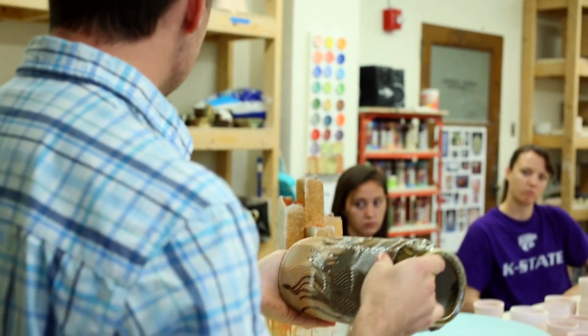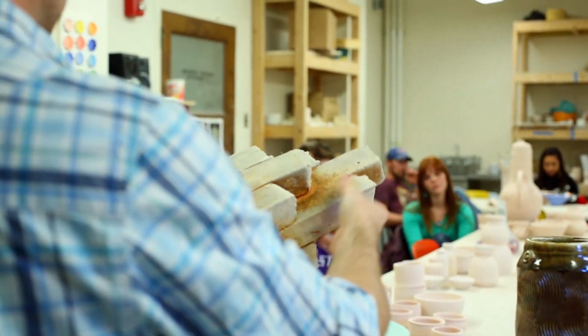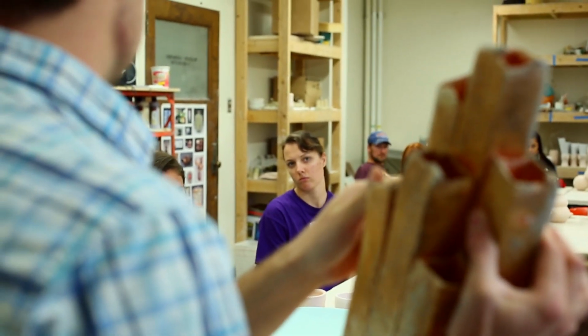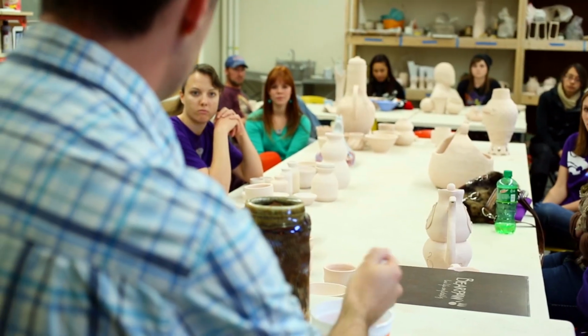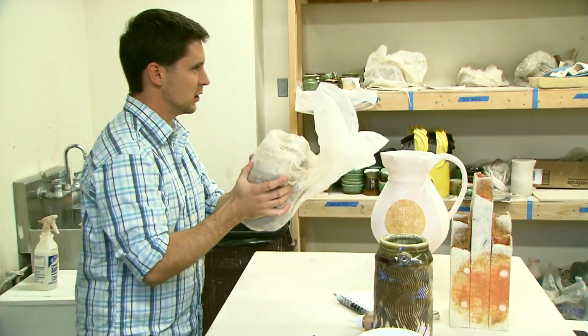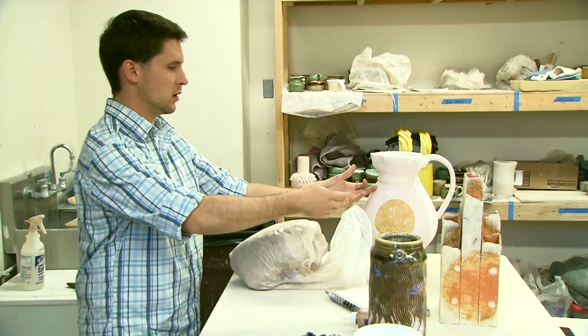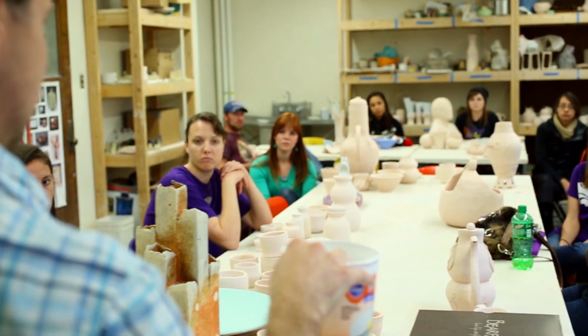You don't get a ton of color with the porcelain versus the stoneware. You get anything from deep oranges where there's not as much soda to whiter, sometimes bluish stuff. And then this stuff right here is wadding. Wadding is just alumina hydrate and kaolin. Kaolin is a clay that we use in our stoneware and everything. The wadding has virtually no silica in it.